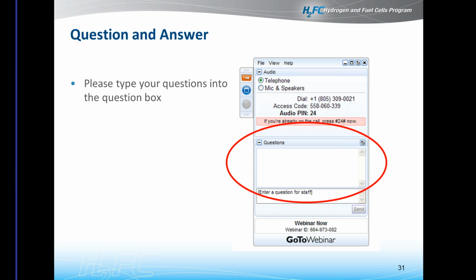Yeah, that's a good question that I probably didn't address well at the very beginning. The current pipelines in use, as I mentioned, are basically operated at constant pressures. They aren't operated at that high of pressures, probably on the order of 1,200 to 1,400, 1,500 psi. We're thinking ahead that we'll probably be operating closer to 3,000 psi when the pipeline economy is much more mature. But really, it is the fluctuations that bring about this other phenomenon.